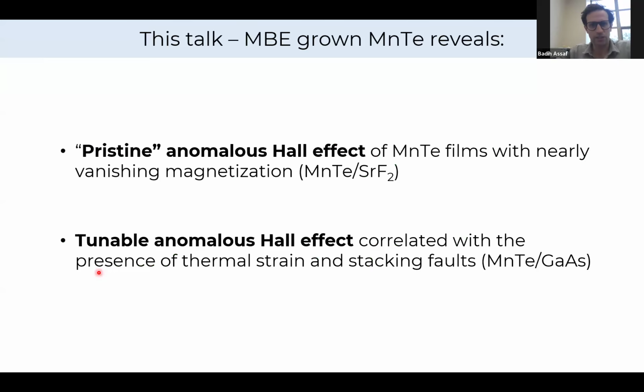So there are two parts in this talk. In the first part, I'm going to show you what I call the pristine anomalous Hall effect of manganese telluride films, which we observe when we grow this material on strontium difluoride, which turns out to be the substrate that has the best compromise for lattice match and thermal expansion coefficient match. It turns out to be important. And then we grew MnTe on gallium arsenide as well, and there we observed a very interesting tunable anomalous Hall effect that we don't understand the origin of, actually. But we correlate its presence to thermal strain and stacking faults. That's what I'm going to show you in a bit.